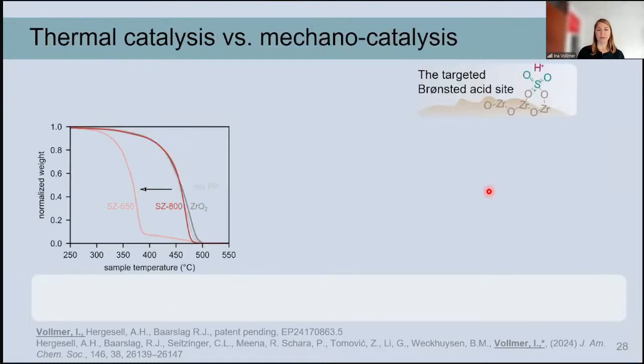So how you can test the thermocatalysis is by using thermogravimetric analysis. What you do is you put the polymer and the catalyst into a very small bucket and you weigh this bucket and then heat it up under nitrogen. And at a certain temperature, the weight will decrease because carbon-carbon bonds are broken. You form smaller molecules which evaporate, and thereby the weight decreases. And this is the curve you can see here.